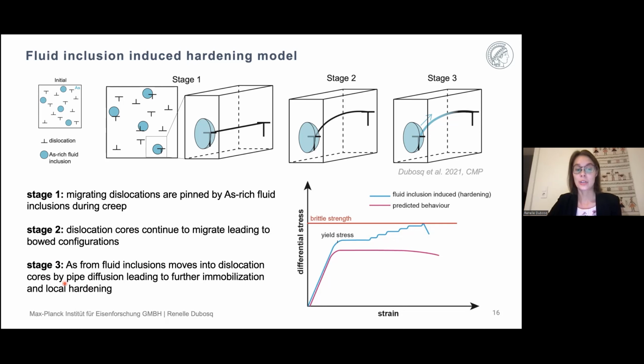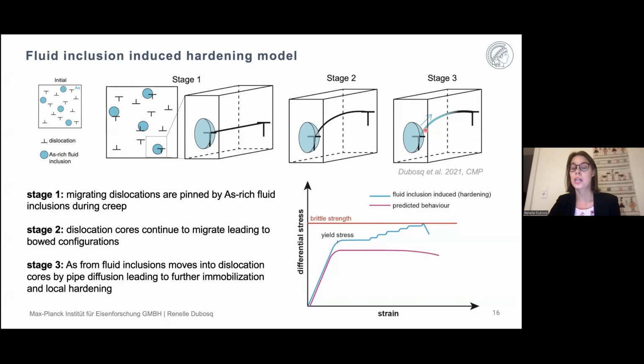And then lastly, in the third stage, we have arsenic from the fluid inclusions here that can move into the dislocation cores by pipe diffusion, which leads to a reduction of the stress field as well as the elasticity of the dislocation, stabilizing it and leading to further immobilization and local hardening in the mineral. So these findings were in contrast to the most commonly reported softening or weakening effect of fluids in minerals.